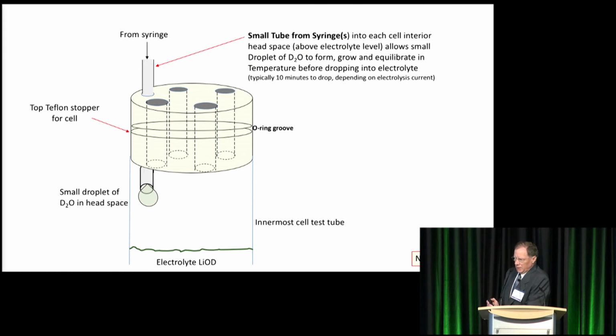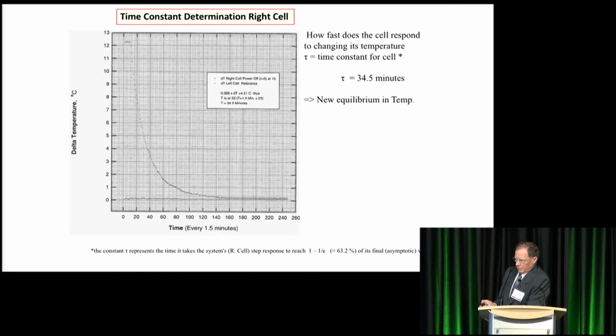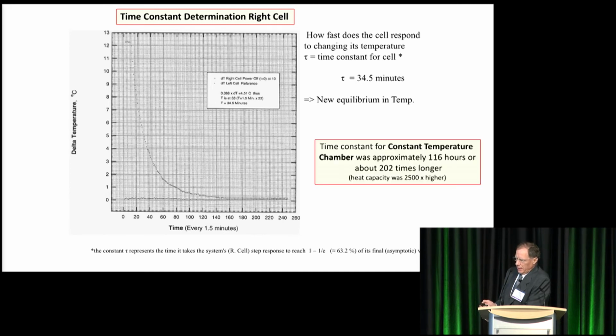The syringe allowed for a small capillary tube to hang a drop of the D2O in the headspace, allow it to sit there and grow and thermally equilibrate before it entered the actual electrolyte. So the electrolyte never knew there was any incoming makeup material. The time constant for the cell was determined in the standard way of 34 minutes. That time constant was also determined for the actual overall chamber of 116 hours. But that was before I added about a ton of Benelex shielding for neutron work, which I spent about 2 years on, which I am not going to talk about. You're not going to coax me into talking about it today.